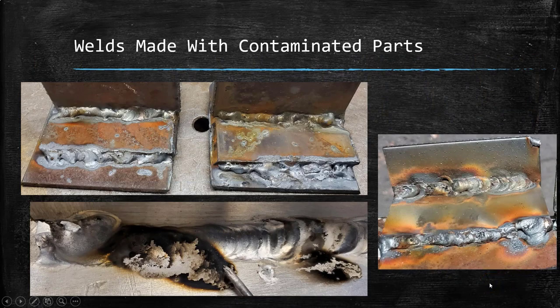And if you continue to try and use a contaminated electrode to weld, this is more than likely what you're gonna get. So we see a couple of different issues going on with these welds. At first glance, an instructor can easily say, you know, in some of these welds, the person welding was doing so without shielding gas, maybe the wrong shielding gas. They were in general using a contaminated tungsten electrode, or maybe their ceramic cup or gas lens had some buildup of contaminants. Maybe they dipped the electrode in a couple of spots, which is more evident when welding aluminum.